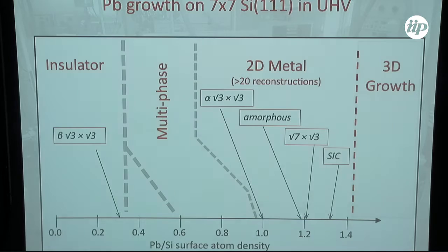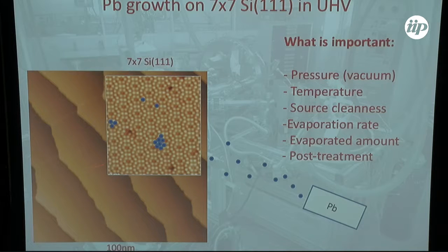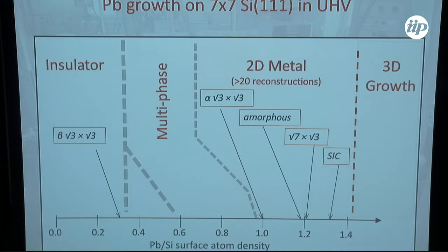So first we prepare, of course, a clean surface of silicon. It is not silicon oxide, it is clean silicon. So these are atomically resolved images of silicon. And we deposit at room temperature atoms of lead with the amount we control with a resolution of about 0.1 monolayer. And then, depending on the average coverage, you have 3 patches in the phase diagram. At a low amount of atoms, you get insulating phases. Then you have some multi-phases where different phases coexist on the same sample.